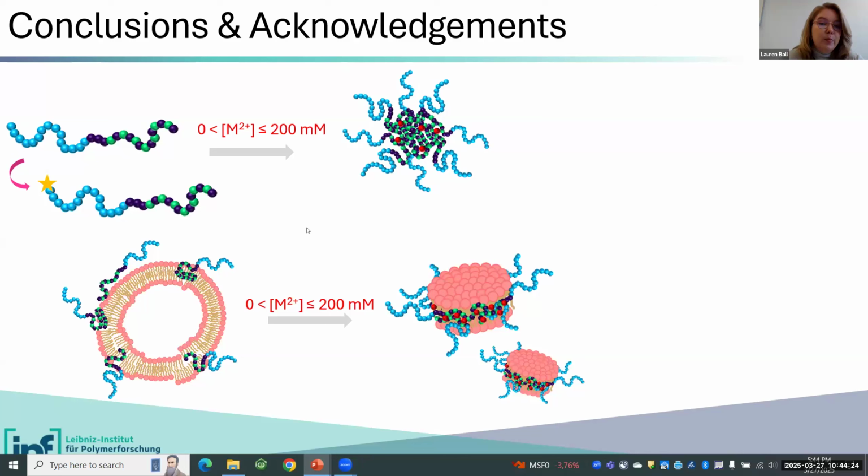And we also showed that these block copolymers under these crazy concentrations of divalent cations can actually successfully interact with phospholipid bilayers, creating SMELPs that are both electrostatically and sterically stabilized. And if you have modified your chain end, these can then be immobilized for subsequent analyses.